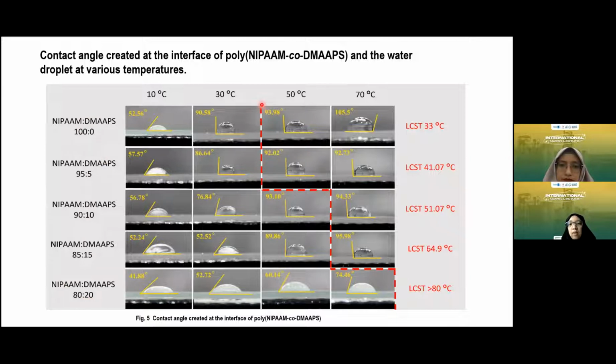As we can see, there are red dashed lines. They denote the temperatures at which the hydrophobicity appears. As we can see, the contact angle on the left side is lower than 90 degrees. However, the right-hand side is higher than 90 degrees. This can be concluded that at temperatures higher than its LCST, the contact angle tends to be higher. That means more hydrophobic.